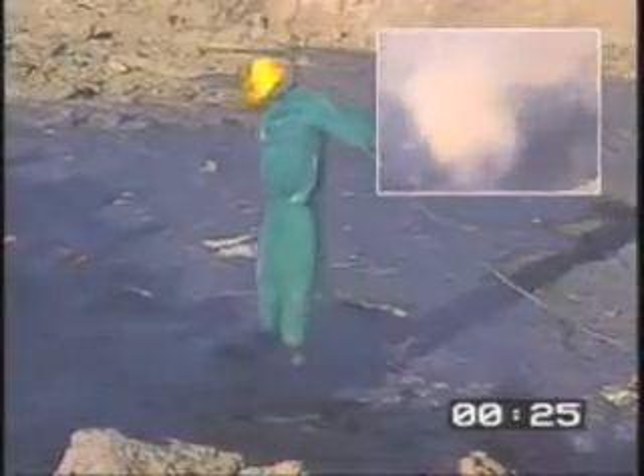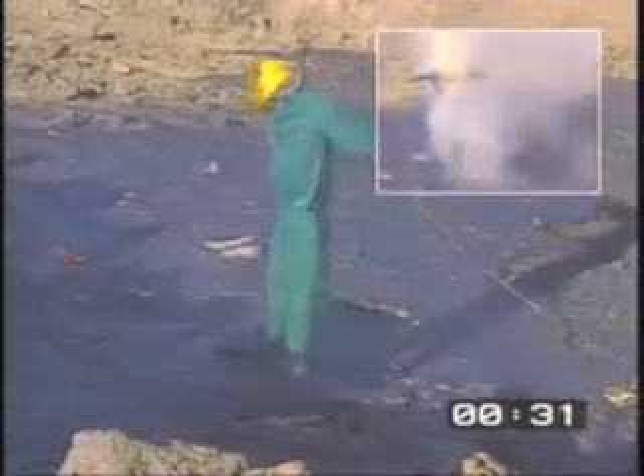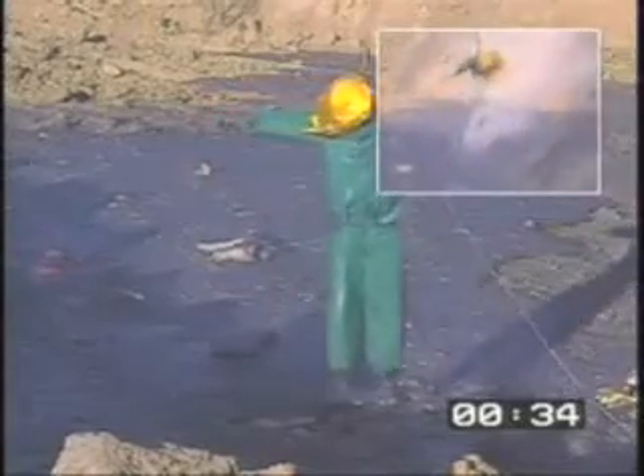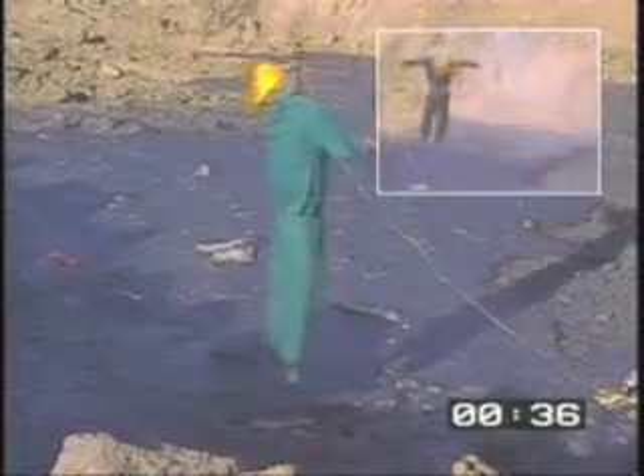After 15 seconds exposure, the dummy protected by Arctic Fire shows no sign of igniting, whereas the unprotected dummy is already on fire. After 30 seconds, the unprotected dummy is completely engulfed by flame. However, the dummy protected by Arctic Fire still remains unaffected by this extreme heat. The Arctic Fire liquid agent only starts to steam off the protected dummy after being exposed to semi-molten slag for a full 2 minutes. The escape hood also remains fully intact and operable, and as we can see, does not catch fire even on the dry dummy.